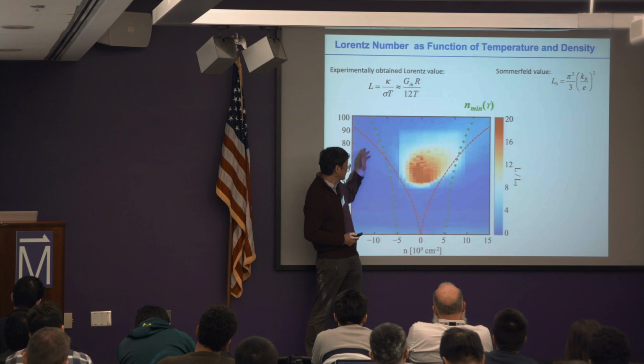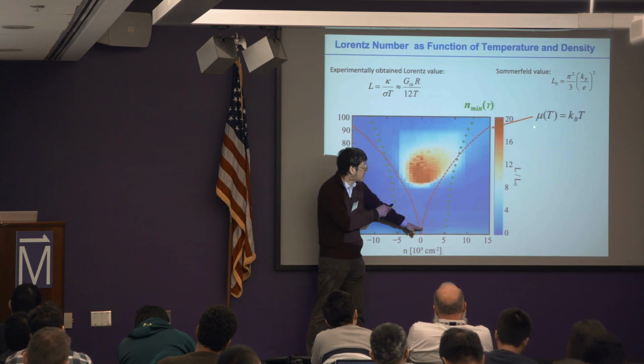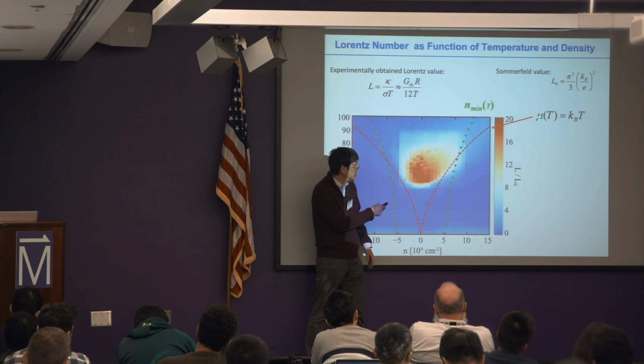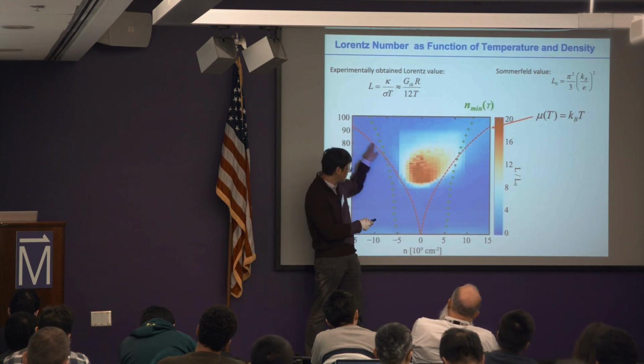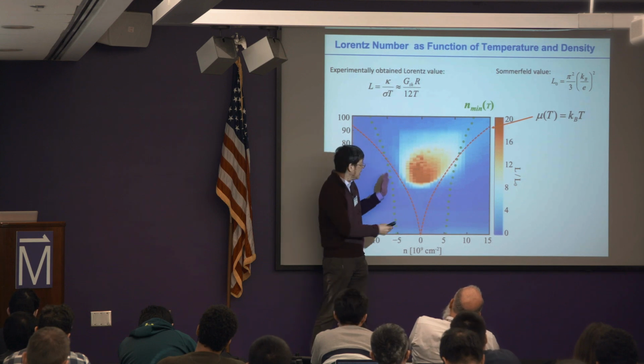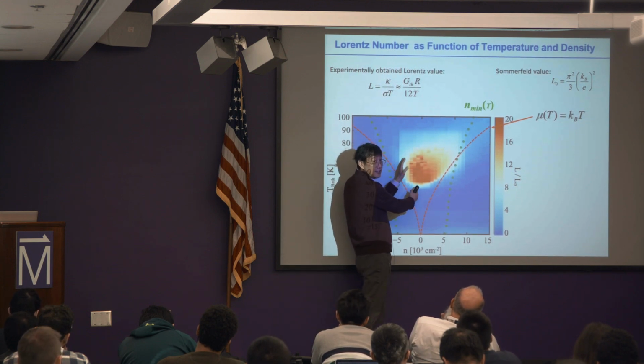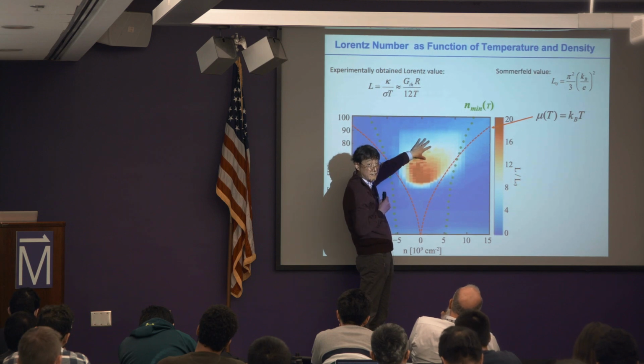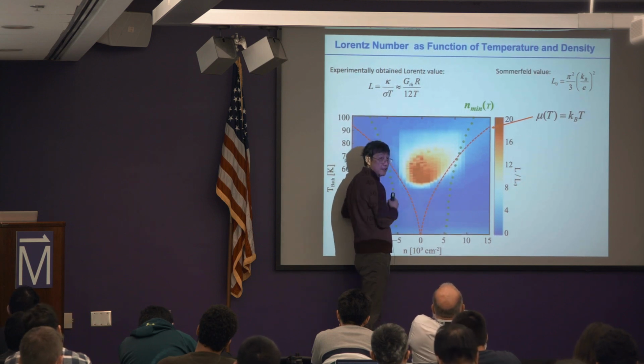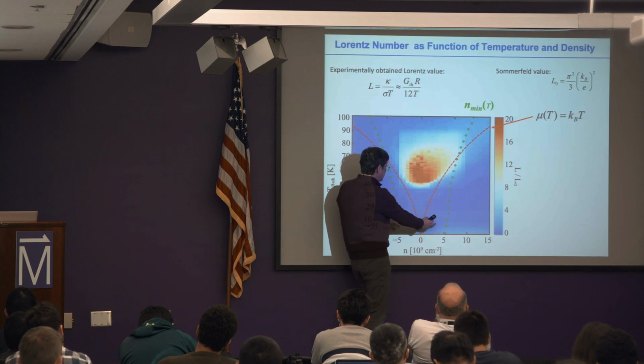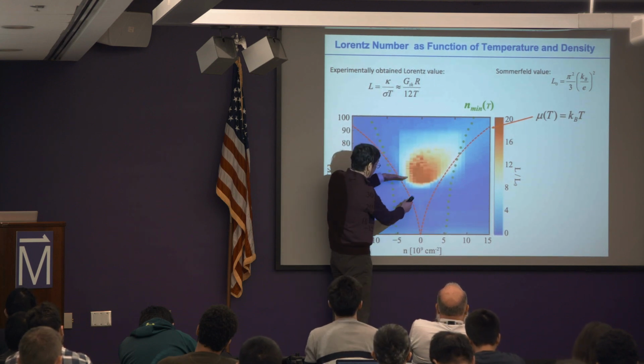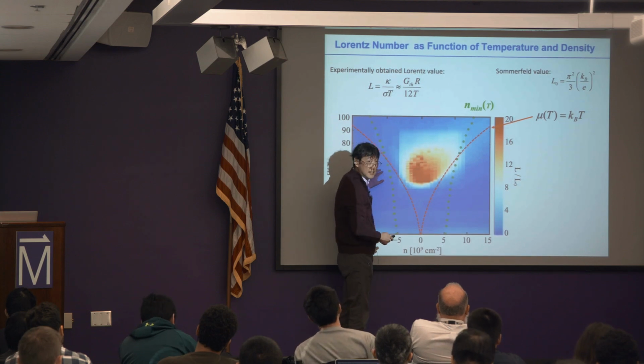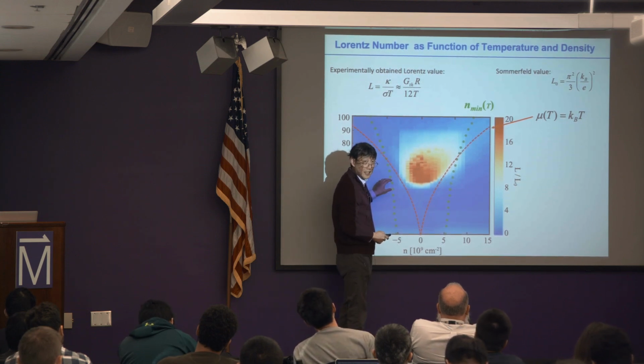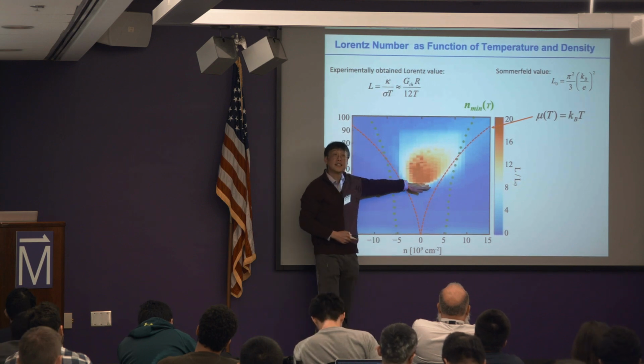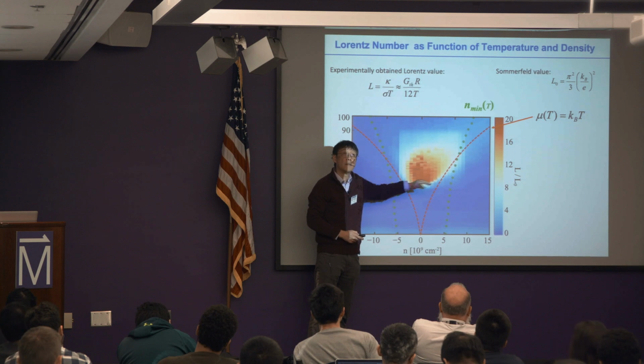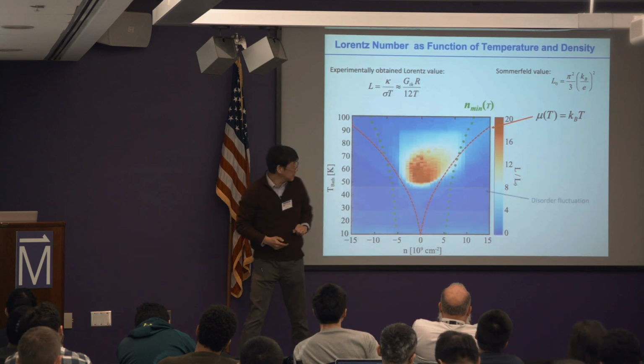For example, I plotted what is the expectation of how the chemical potential changes in the sample. Basically, using the dispersion relation, this shows a square-root type of behavior, right? In between this conical section is ideally where I expect to see the non-degenerate carrier system. Outside of here, I expect to see the Fermi liquid, right? And now the experimentally measured value of this curve tells us that around this temperature is where disorder is more dominant. In other words, the deviation of the Wiedemann-Franz law is lower bounded by where disorder dominates, in terms of temperature.